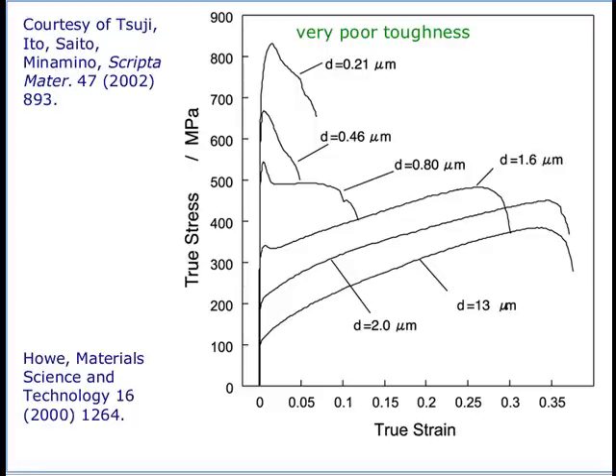So in addition to making the crystal size smaller, we have to introduce some mechanism for work hardening. Because if you do not do that, then you get a plastic instability and your material will fracture at a low elongation. Now, how do you do that, okay?